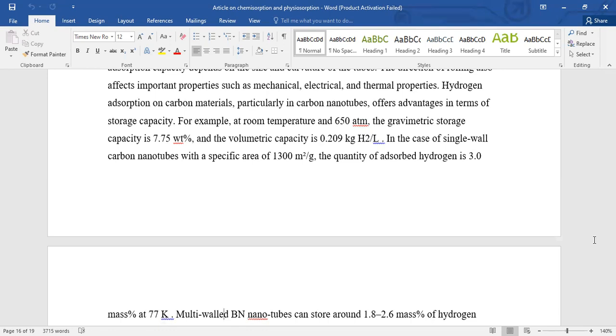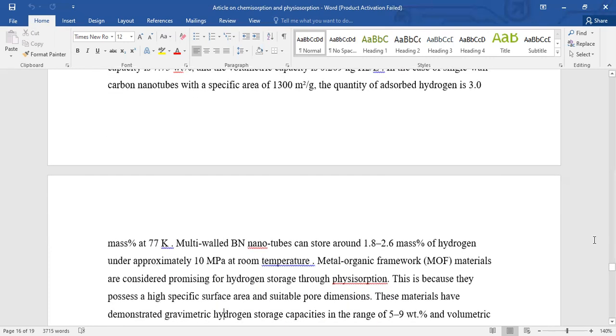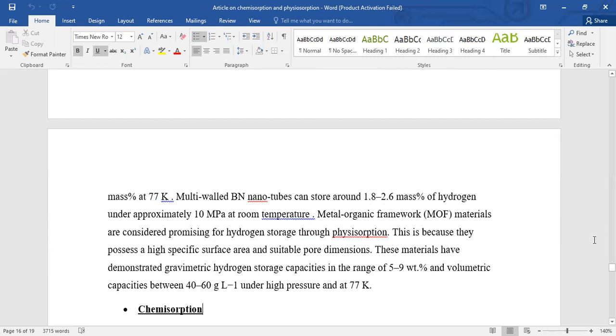In the case of single-wall carbon nanotubes with a specific area of 1300 square meters per gram, the quantity of adsorbed hydrogen is 3% at 77 Kelvin. Multi-walled nanotubes store around 1.8 to 2.6 mass percent of hydrogen under approximately 10 megapascal at room temperature. Metal organic framework materials are considered promising for hydrogen storage through physisorption.